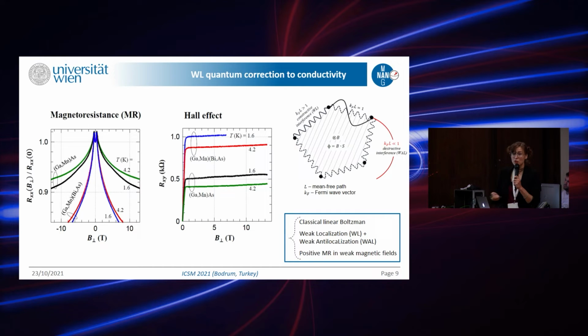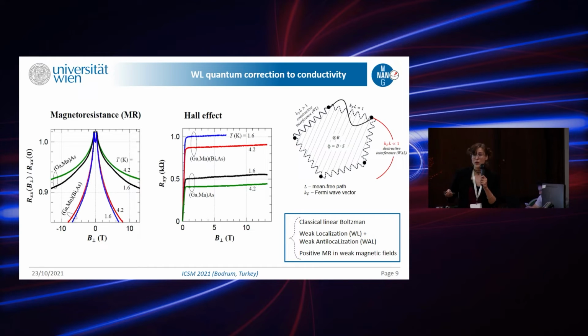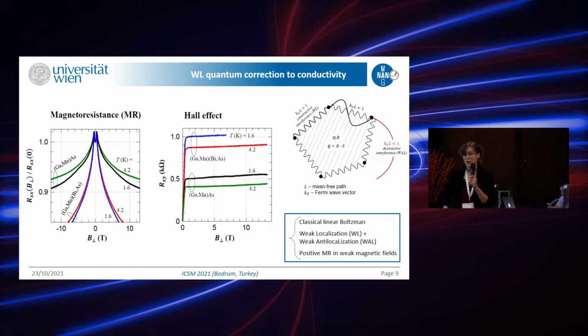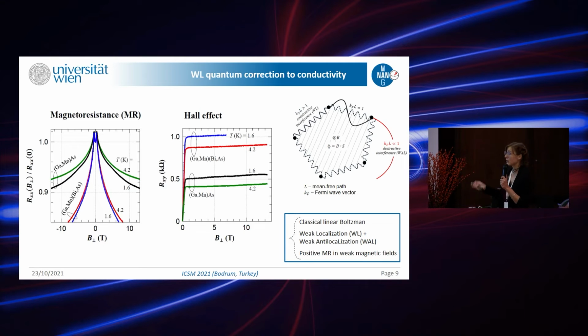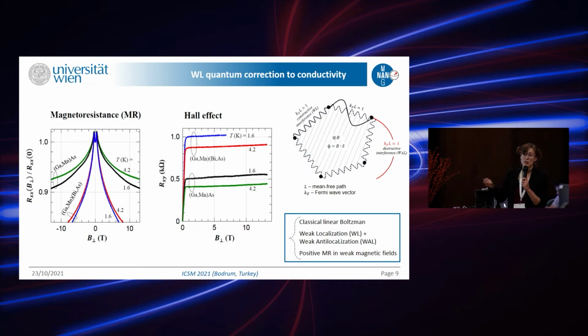But for this, we would like to concentrate on the middle segment, to characterize weak localization and anti-localization, which are both phenomena connected to the fact that when the charge carrier is propagating, it goes through self-intersecting paths. And depending on whether you have constructive or destructive interference, you will have either addition or reduction of your resistance, which is basically the weak localization. And it's classical for materials with a high disorder, or generally with a disorder, or driven by spin-orbit coupling.